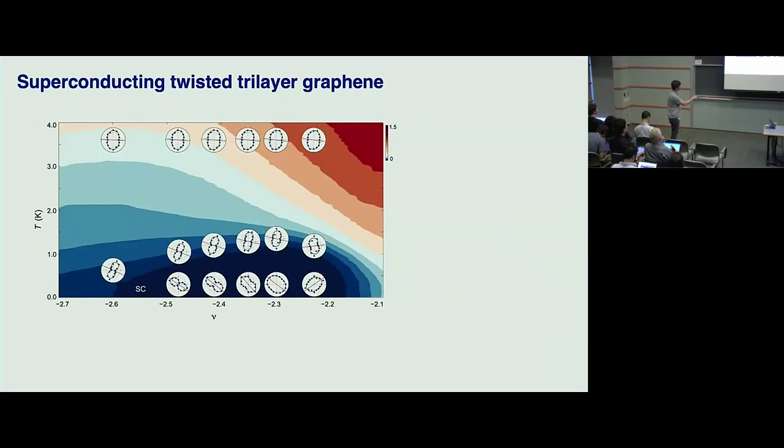And if you do this over the entire superconducting dome, the observation is similar: in the normal state here, at 4 Kelvin, there's anisotropy, but the anisotropy axis is density independent. And as you cool down near the superconducting phase in the fluctuation regime, you can see that this anisotropy becomes stronger and the axis starts to rotate, right? And we can compare this to the critical current in the superconducting phase. The easy axis of the superconducting phase with the largest critical current aligns with the principal axis with the lowest resistance, right?